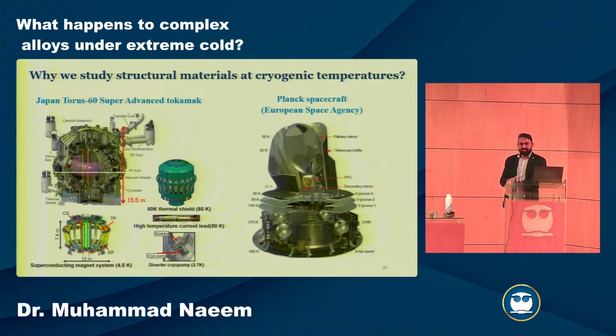Then I would just mention very quickly, Sandy already mentioned the tokamak fusion reactors, an application where we need very low temperature. This is a Japan Superconducting Tokamak 60, and it lists the components and the temperature at which these components operate. For example, this thermal shield will operate at 80 Kelvin. Then there are some other components at 50 or 4.5, even 3.7 Kelvin.